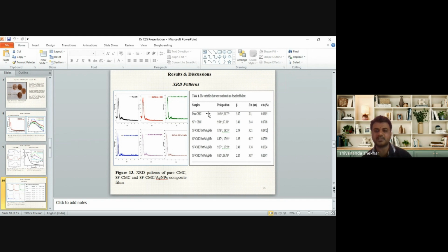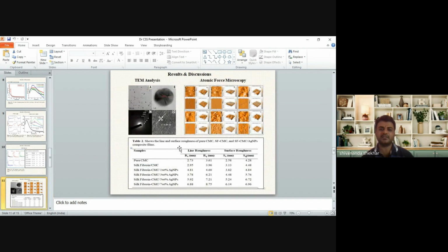So these are the parameters we have evaluated using XRD graphs. We found the peak position, and we calculated the peak width and also the crystallite size using the Debye-Scherrer formula. We have calculated the different crystallite sizes as well as the lattice strain. Then we have done the TEM analysis and also atomic force microscopy.